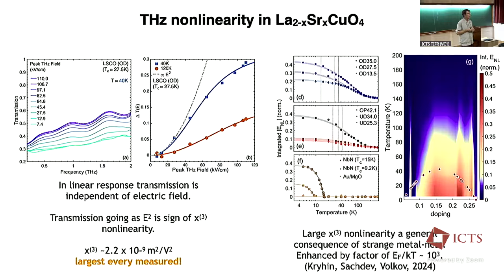The phonons do go out of their equilibrium distribution. Is that a major thing to take into account in a quantitative description of the data? I think probably not. The optical phonons? I actually don't know, but the optical phonons are not going to play a strong role here because we're at much lower energies, below all of them. So it's the acoustic phonons that we're coupling to primarily, I would guess. There's a whole host of optical phonon modes, which start in the tens of meV range, but are probably peaked around 20, 30, 40 meV.